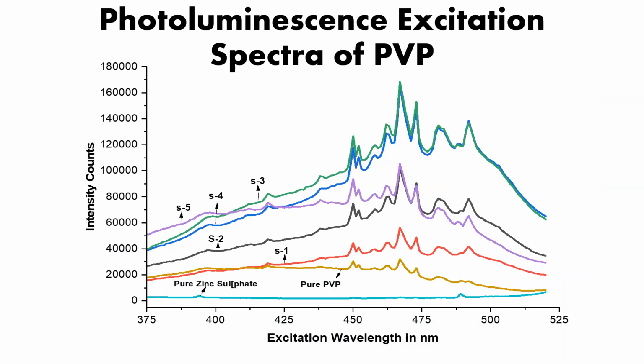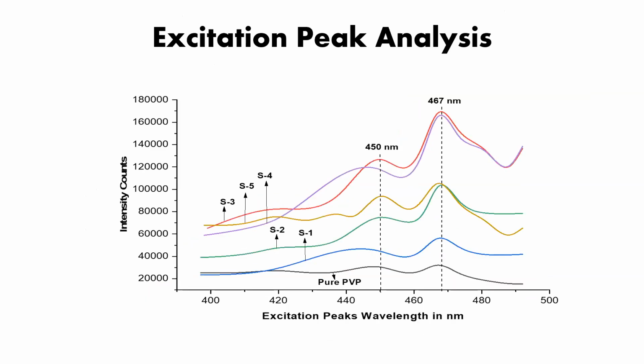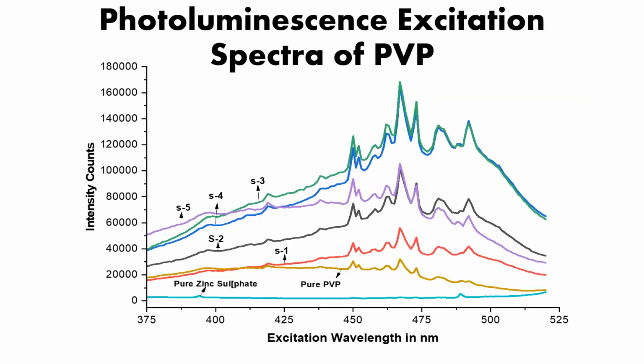And here I found that we need to use a specific excitation value. Previously we were not aware of which value I should use for the excitation of my sample. So during my mathematical modeling, on the basis of this peak analysis, I used mathematical modeling with the Origin software. I analyzed these excitation spectra, the peak value of excitation wavelength with its intensity counts, and put it